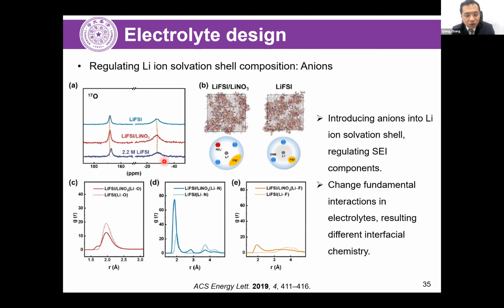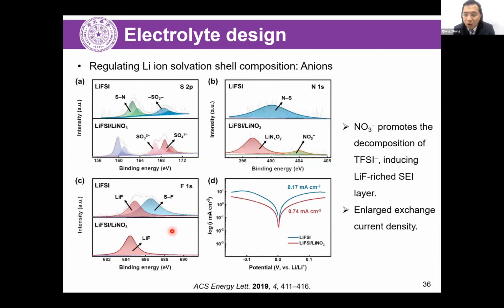And we also get the distribution of the lithium-oxygen, lithium-nitrogen, and lithium-fluoride coordination. And it is found that these items prefer to interlink with lithium easily. And once the ion complex receives electrons, then it helps the decomposition of the ions quite easily. This will introduce a lot of nitrogen oxide products on the lithium metal anodes. Also, lithium fluoride can be observed in large amounts.